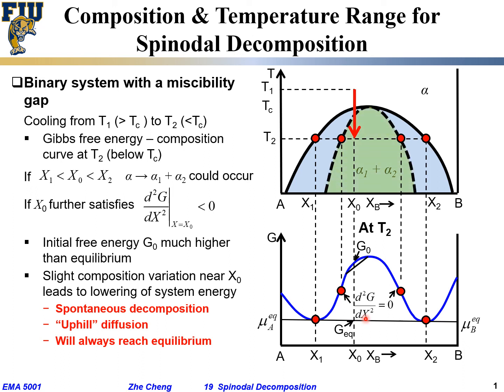If we do this analysis at all different temperatures, we get a dashed line on the phase diagram. All these dashed lines correspond to where the second derivative equals zero at different temperatures. Connecting them gives the so-called chemical spinodal composition boundary. If the initial composition is between the dashed portion, the material going from single phase alpha to alpha 1 plus alpha 2 will go through the spinodal decomposition process — involving uphill diffusion and a spontaneous transformation that does not create a distinct interface at the beginning stage.